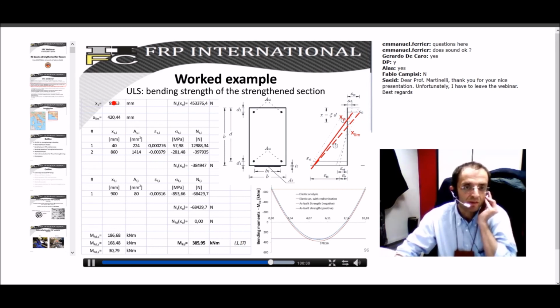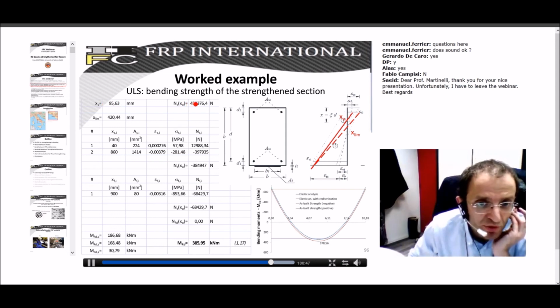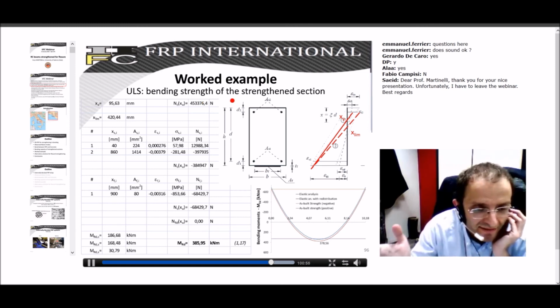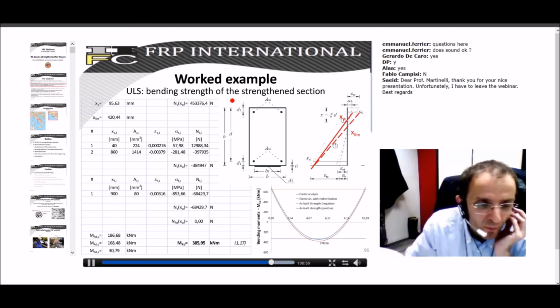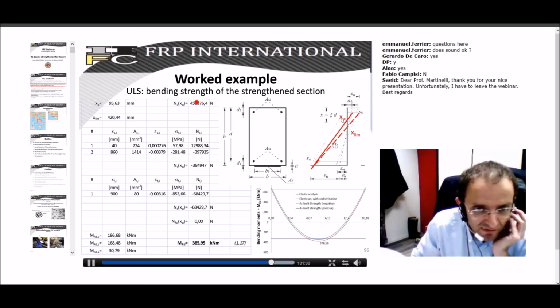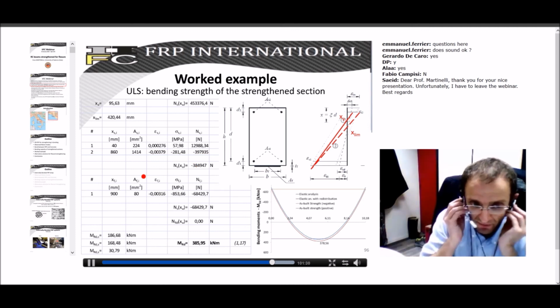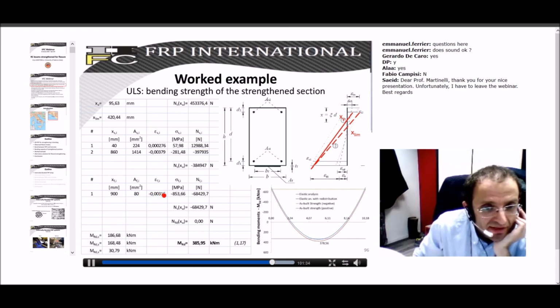So, for instance, we can evaluate the position of the neutral axis, which at the end we will find to be 95. Why is it 95? Because we have a contribution of concrete which is evaluated according to the conventional stress block: the strength of the concrete times the width of the section times 0.8 times XU you have here. Then this is the contribution of the internal strengthening, the internal rebars. So you have the top rebar, the small one, no? This is the small area, resulting in this contribution, in compression. The bottom one with this neutral axis, this is the tensile strain, and this is the corresponding strength. This is the resulting force in the steel rebars, top and bottom. These are also the epsilon Fy.